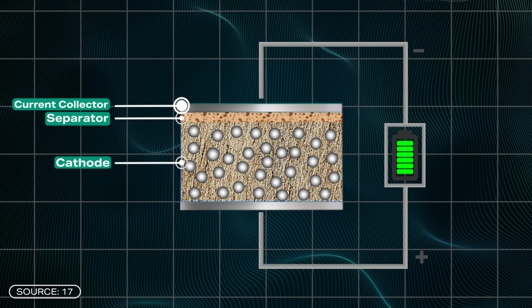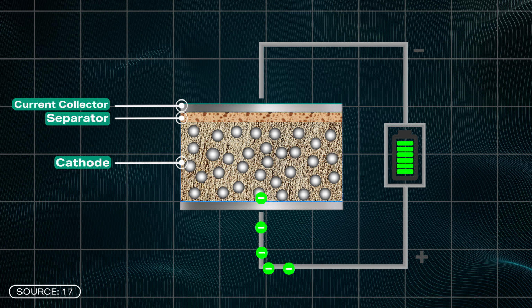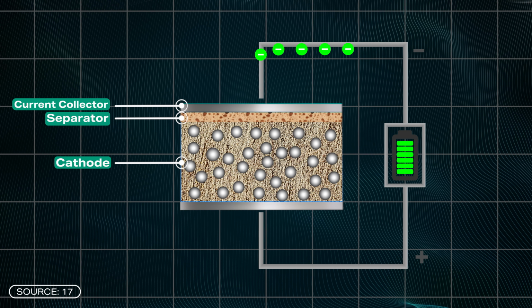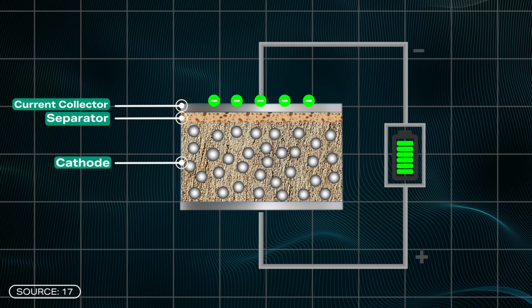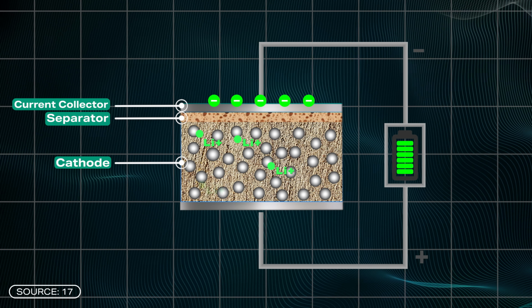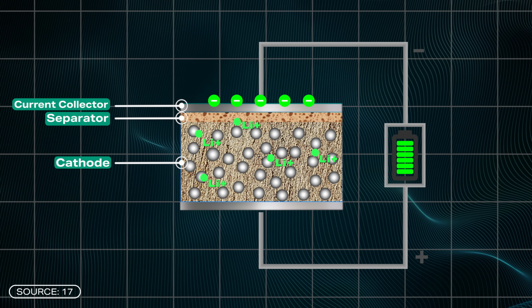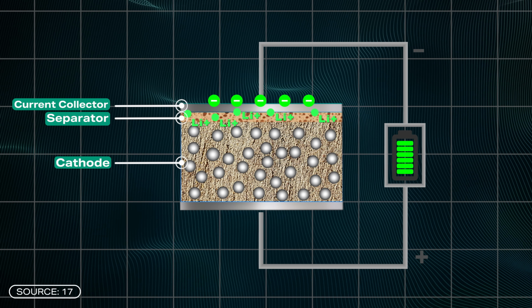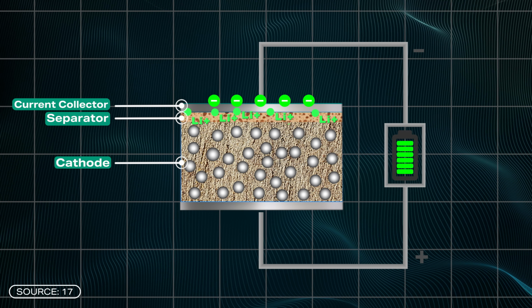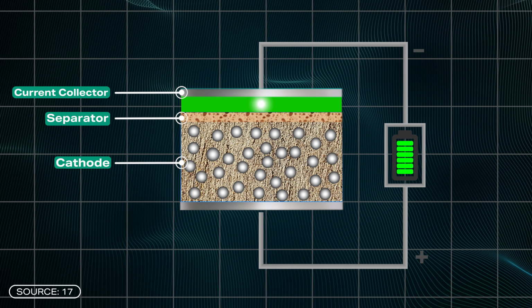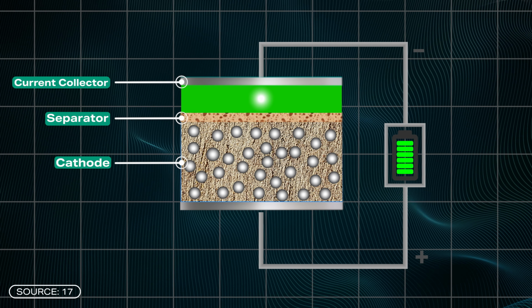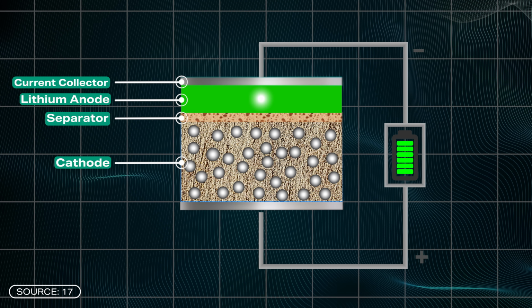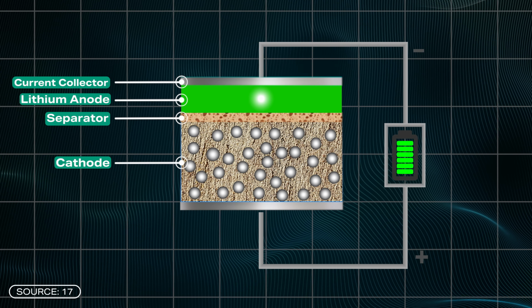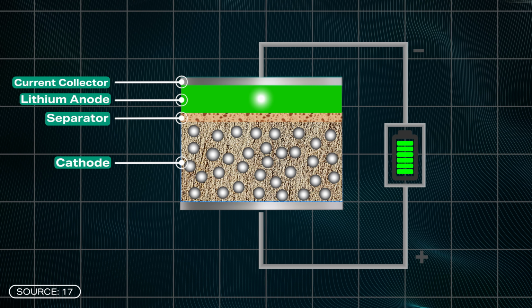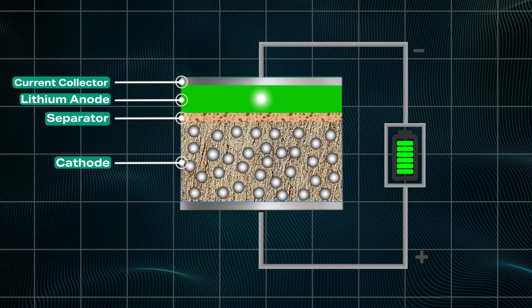You can visualize the formation of the lithium anode on this metal foil as follows. As soon as a voltage is applied to the battery, electrons migrate via the outer circuit from the lithium-containing cathode to the anode side. However, the charges are then unevenly distributed and must be balanced. That is why the positively charged lithium ions migrate from the cathode to the current collector on the other side. The electrons are essentially waiting there and they then combine with the positively charged lithium ions. This creates lithium, which is then deposited on the current collector. So now we have a thin layer of lithium on the current collector, an anode.